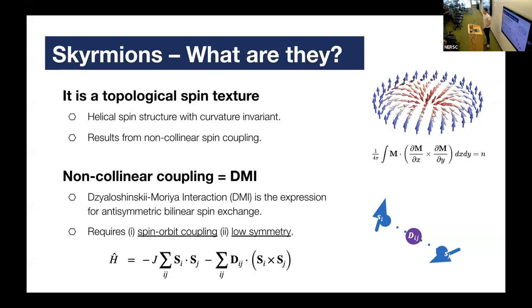So what actually leads to the formation of these kinds of textures is essentially an interplay between two different exchanges between neighboring atoms within the material. And so one is the direct exchange, which is this J term. That's the one that, depending on the sign of it, it either wants to make the spins agree between neighbors or disagree, which would be a negative case. Then the one that's more fascinating for us is this anti-symmetric exchange here, which is the D_ij. So it's related with this cross product. It's a vectorial quantity. And so that's the one that you can think of, and I was hoping to try and illustrate with the diagram, is that it's the one that actually makes it want to point at 90 degrees, which is where the cross product would be easier. And so it actually originates from the same place as J would, which is a result of spin orbit coupling. But it also requires in order to not cancel out a low symmetry to the structure.